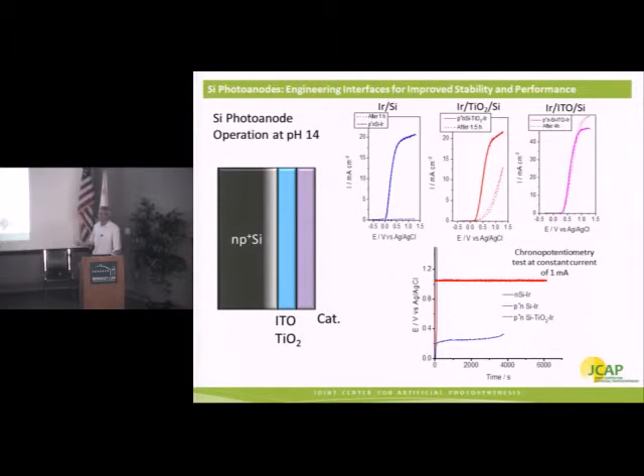So it's not complete degradation, as is the case when you don't have the TiO2 layer at all, but it's not stable. Finally, we've deposited ITO onto the surface of the silicon. This, again, is more or less conformal on the surface. Iridium on the surface of that we've tested.